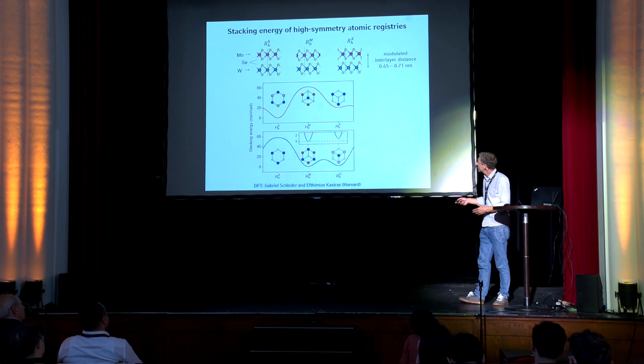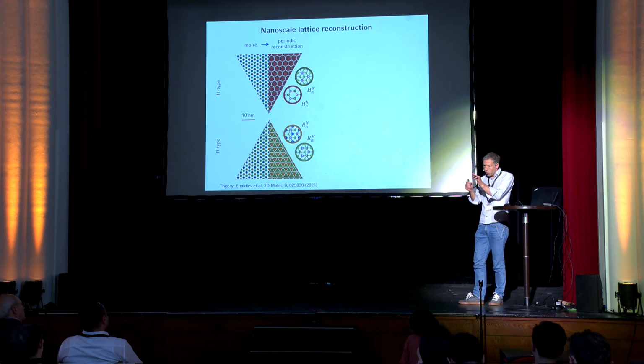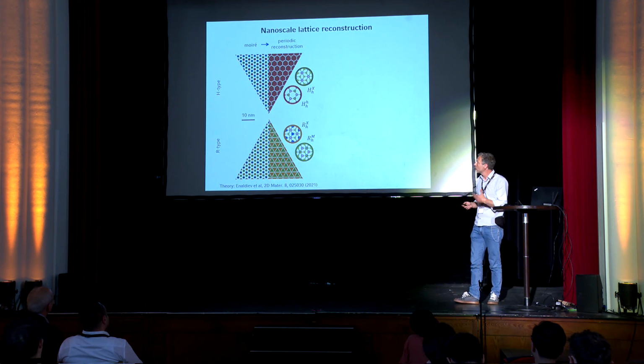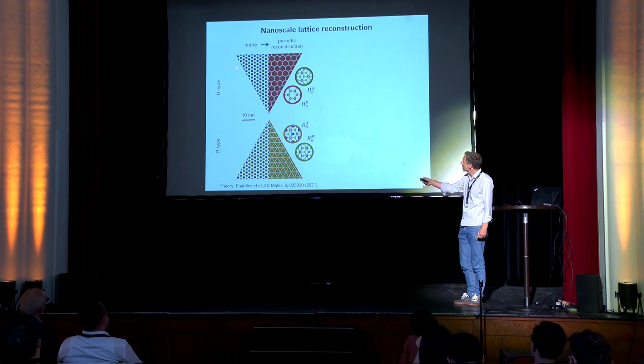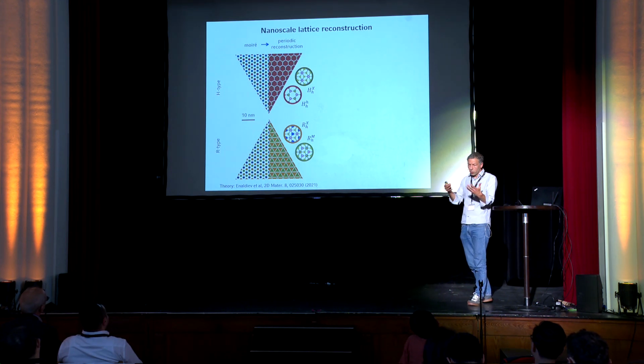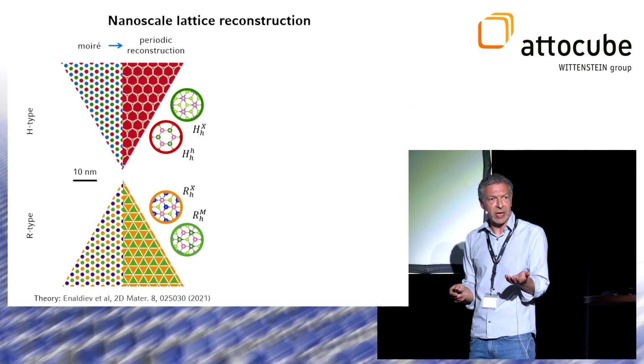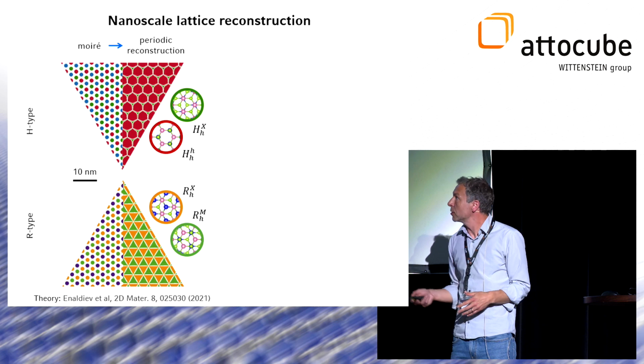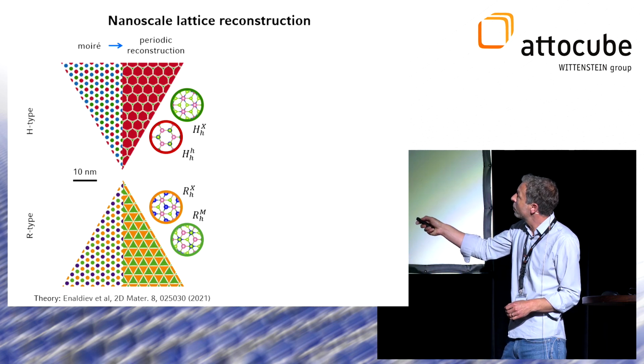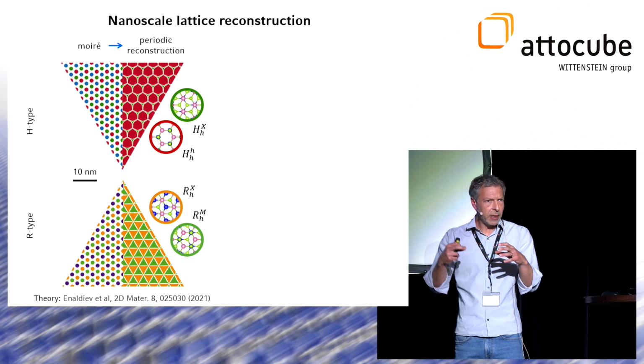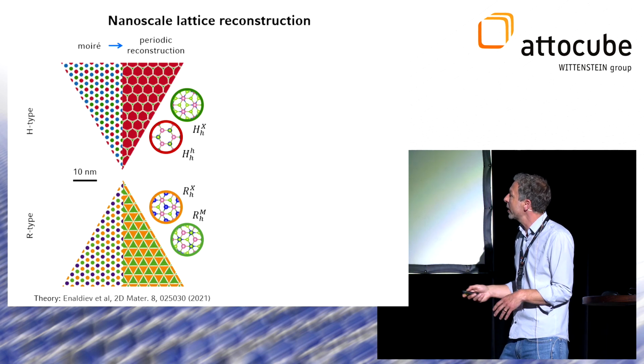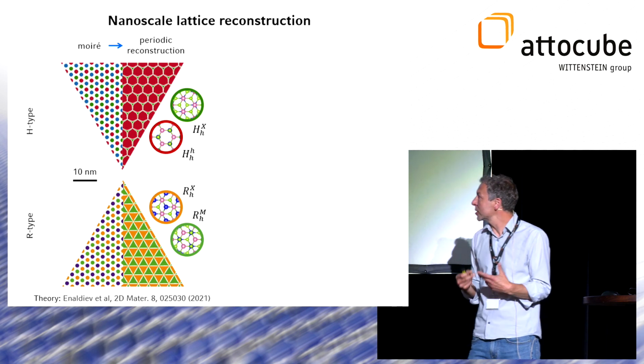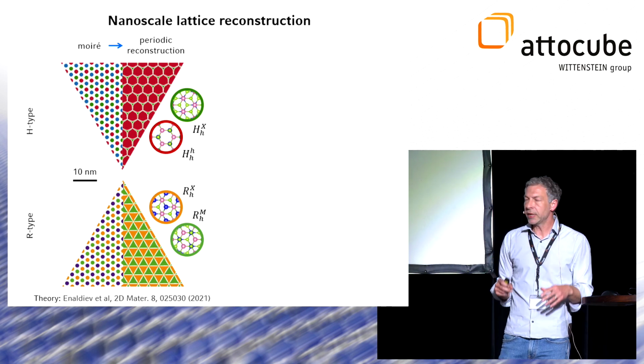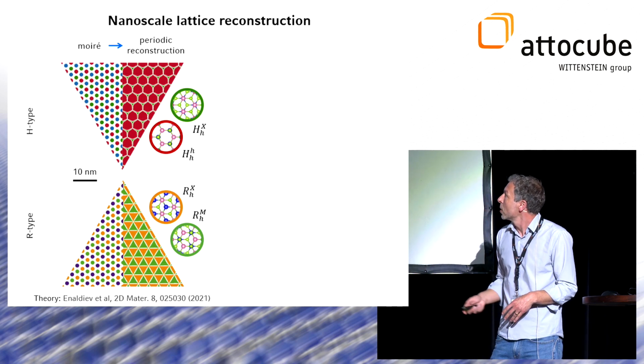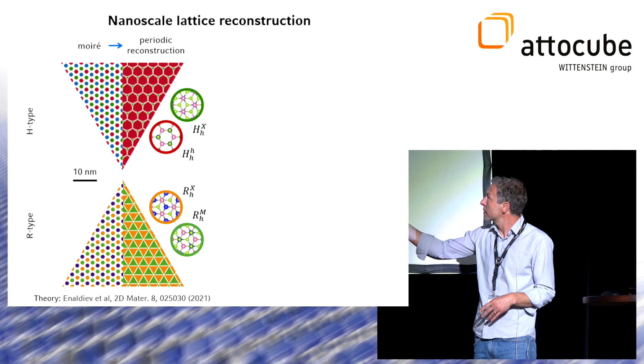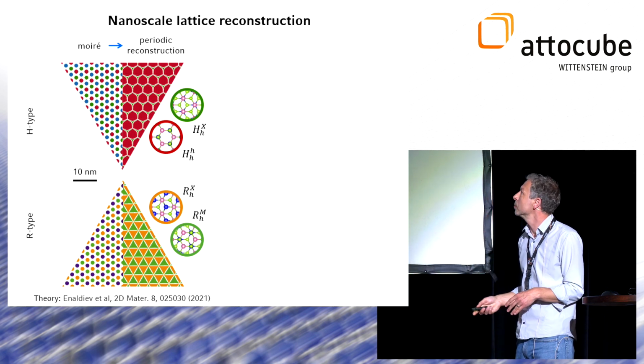And once adhesion wins over strain, we have local rearrangement of atoms, and theory has it that an ideal canonical moiré system would reconstruct according to this displacement in something that is again periodic, so it's extended in two dimensions. For the anti-parallel stacking, a hexagonal tiling of reconstructed patterns is predicted, whereas for R-type samples, or parallel alignment, there is a triangular tiling of this periodic reconstruction. So note the length scale here, 10 nanometers. This is a characteristic scale of the moiré unit cell in such systems.